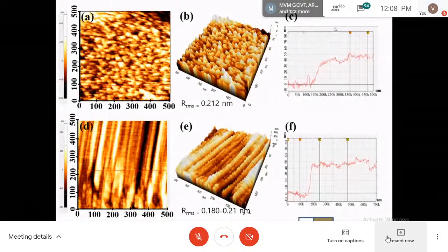And also, this is the line scanning profile called alpha step. It is an instrument for when the thickness is very small. After 10 minutes or 7.5 minutes coating of cyclohexane, the coating thickness is very small. We cannot even measure using FESEM because FESEM uses electron bombardment, so the coating will easily degrade. So we cannot utilize FESEM for thickness measurement. So we have to go for other techniques such as this alpha step.